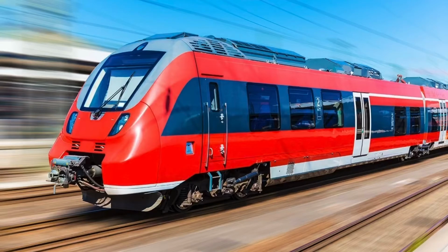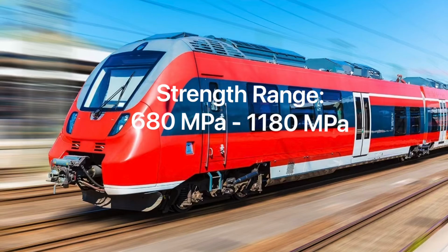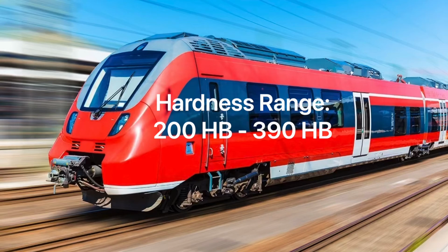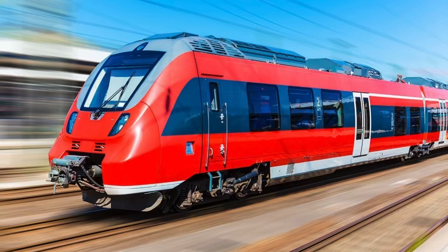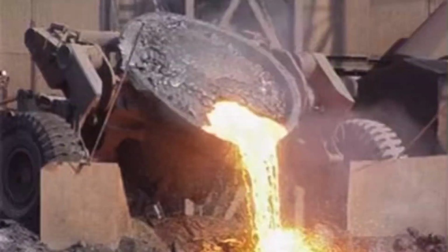The closeness of the lamellar within the structure also plays a role, as the closer they appear, the stronger the steel. The strength rating often ranges from 680 megapascals to 1,180 megapascals, while the hardness ranges from 200 Brinell hardness to 390 Brinell hardness, depending on the specificities of the heat treating process, such as time, temperature, and the cooling rate and process used to manufacture the steel before it is turned to rail lines.